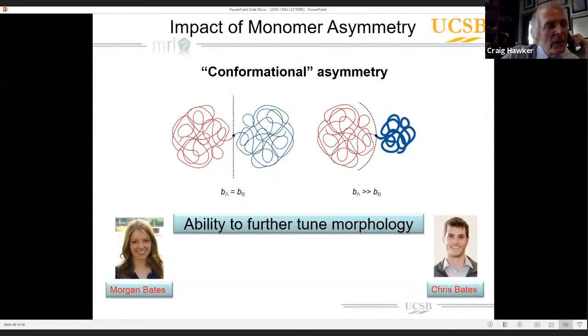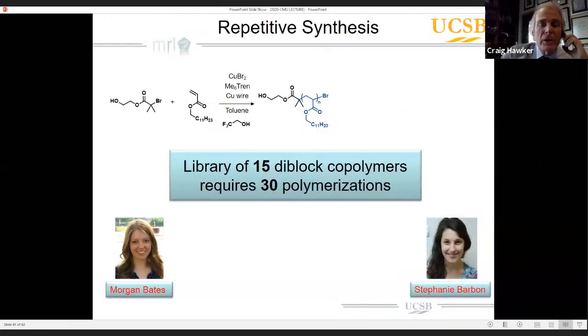But again, it's really good to have young colleagues, and I'm very fortunate to have Morgan Bates and Chris Bates as young colleagues here at UCSB. They corrected me and told me that I was wrong, and that chi-N and the fraction are not the only things that really dictate morphology. You can actually tune it with other parameters such as conformational asymmetry, basically the thickness of the polymer chains. And if you choose your monomer units correctly, you can really have significant asymmetry between these two chains. And so this is another tool to tune morphology.